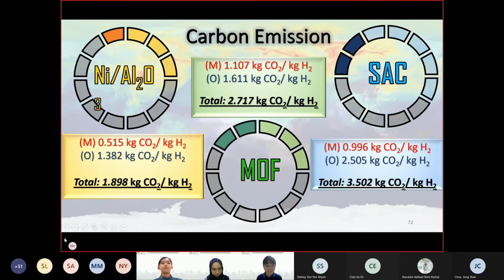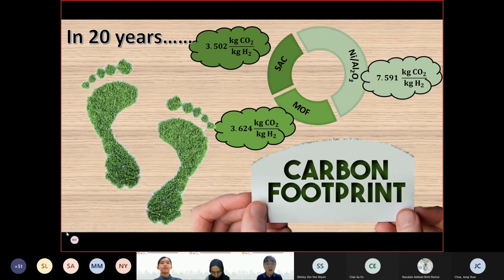Moving on to environmental analysis, it can be analyzed on the carbon emission from the synthesis of the catalyst. From here, carbon emission from the single-atom catalyst, nickel HAP, is actually the highest, as compared to the conventional and MOF-based catalysts. However, in account of a 20 years project lifespan, the carbon footprint observed from nickel alumina catalyst is about double of the novel catalyst. This further validates the potential of the proposed novel catalyst in carbon dioxide mitigation.